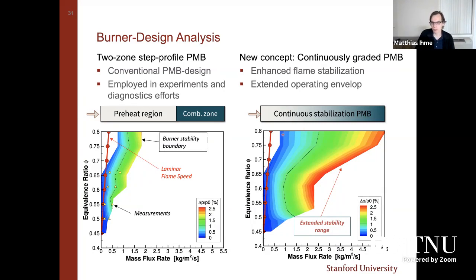Here, computation results show this color-coded region is the stable regime, and you're seeing right away that from a stability range of about 2 kilograms per square meter per second mass flow rate, we can extend this almost by a factor of 3, making this a rather interesting porous media burner design for this application. All right. So here the key message is that we can significantly extend the stability limit for this burner. And at the same time, as I'll show you in a second, we can also reduce the emissions simply by taking advantage of this broader operation regime by allowing this flame to stabilize at different locations. And this is essentially facilitated by this continuously graded burner design.